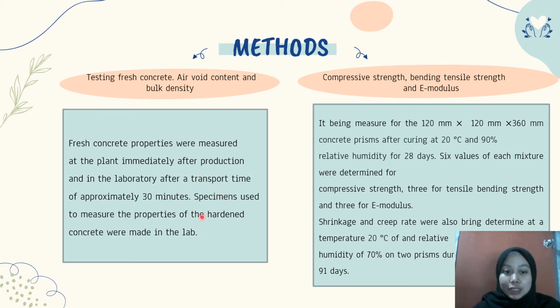Specimens used to measure the properties of the hardened concrete were made in the lab. And then the methods used are compressive strength, bending tensile strength, and E modulus. They were measured on 120 mm times 120 mm times 360 mm concrete prisms after curing at 20 degrees Celsius and 90% relative humidity for 28 days. Six values of each mixture were determined for compressive strength, 3 for tensile bending strength, and 3 for E modulus. Shrinkage and creep rate were also determined at a temperature of 20 degrees Celsius and relative humidity of 70% on prisms during 91 days.